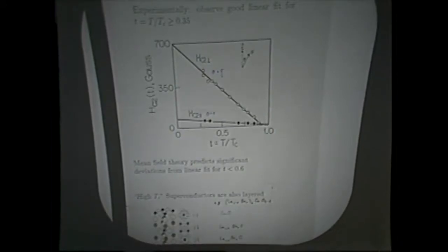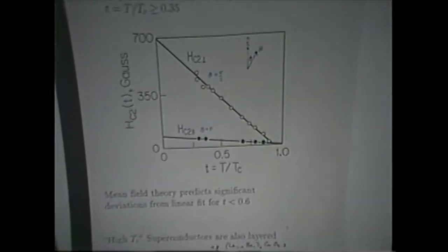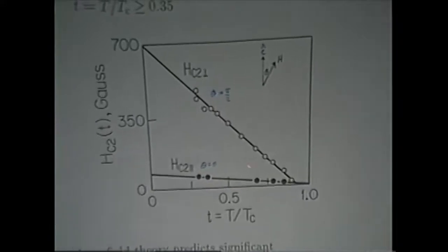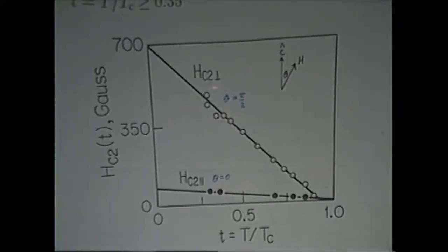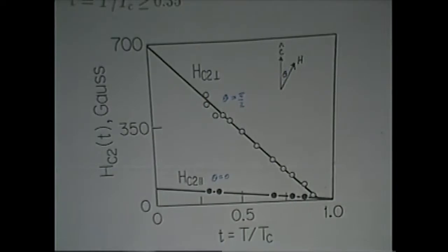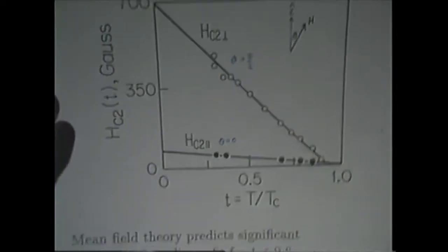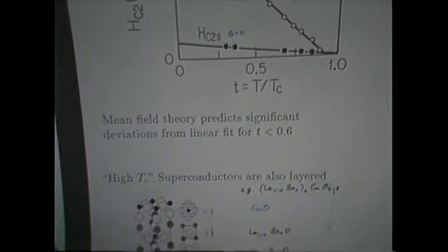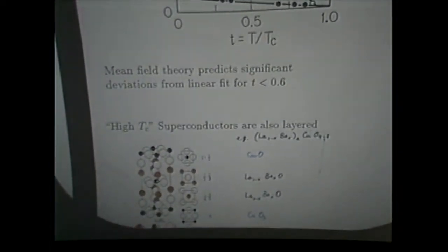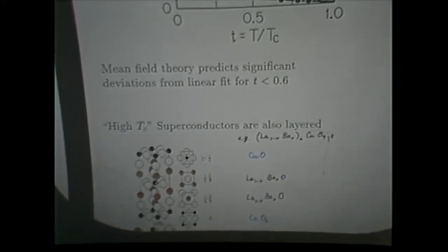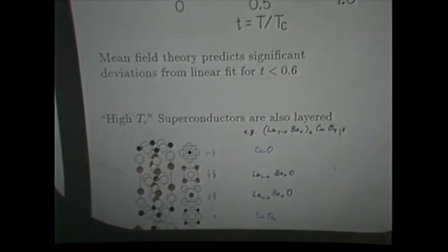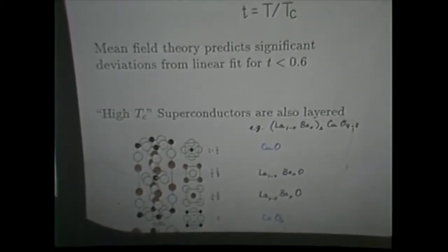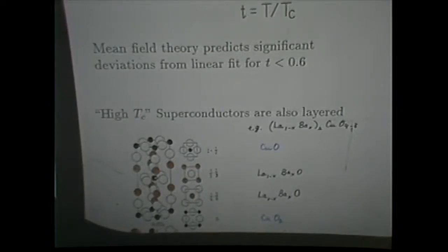The temperature dependence of the critical field is supposed to go like this. It's supposed to have saturated at low temperatures. But for as low in temperature as we've gone so far, it seems to be linear. The data's kind of noisy, but we're still going way lower than what you would expect for a linear dependence. So right now we're headed in two directions, going to higher stages to look for more anisotropy effects, and hopefully to get into the region where the coherence distance will become less than a lattice constant.